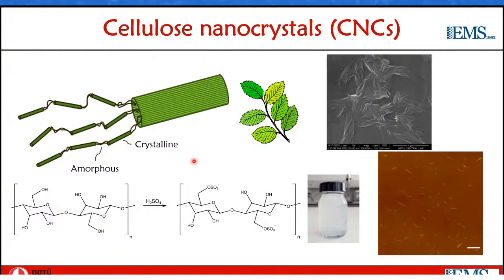When we subject native cellulose to a concentrated mineral acid, the amorphous regions are decomposed and degraded, and what we end up with is only the crystalline regions, which are nanorods of 10 to 20 nanometers diameter and about 200 or so nanometers length, such as those seen in the SEM image here and the AFM image here. When the concentrated acid we use is sulfuric acid, during this process, the hydroxyl groups on the surface of the nanocrystals are partly converted to sulfate half esters, which gives the nanocrystals a net negative charge and also good colloidal stability.